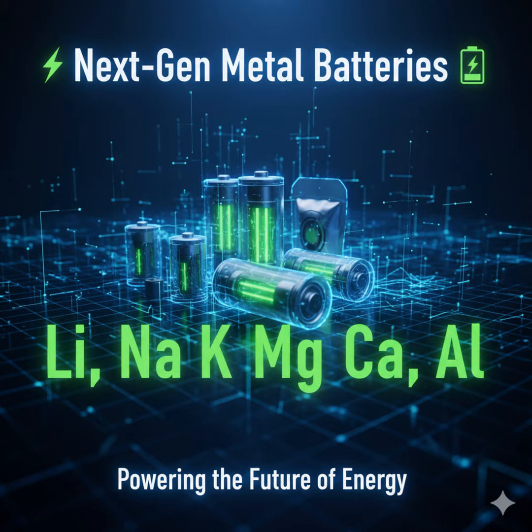Okay, vicious vines for the monovalents. What about the multivalents? Magnesium, aluminum. They behave differently. Their growth is usually less dramatic. Because they have higher surface energies and different crystal structures, like magnesium is hexagonal close-packed, lithium is body-centered cubic. They tend to form things like interconnected platelets and random fibers or spheres.